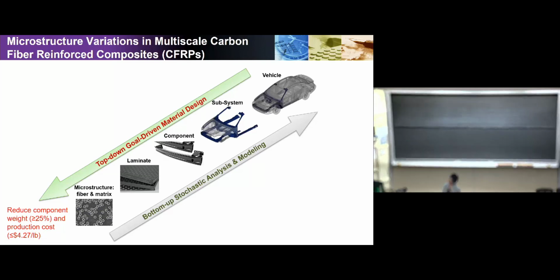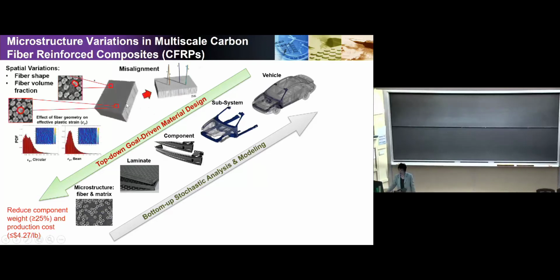But in reality, they're very different. And one major source of the difference or variation is actually caused by manufacturing. Because if you think about a part that has a shape, after you apply the manufacturing processing condition, at each different location the structure can be very different. For example, the fiber angle is different at different locations after you do the preforming. So how do you take that variation into account?